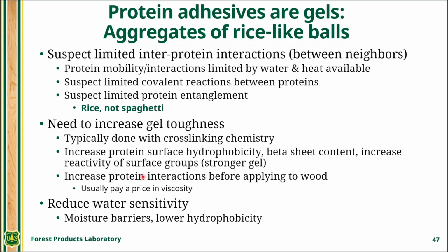We suspect there's limited covalent reactions between the proteins. As far as anything other than disulfide bonds, I don't think there's much of that happening between proteins unless you add a cross-linking agent. And we suspect there's very limited protein entanglement between neighboring proteins. If you can get polymer entanglement, that's a great way to develop strength. We need to increase the gel toughness. Typically, this is done with cross-linking agents.